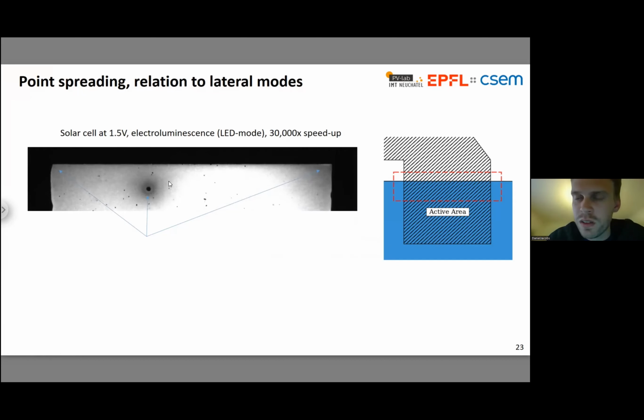So this was a solar cell device in which I stressed it at forward bias. It's an LED type test where I was applying forward voltage and just looking at the electroluminescence. The schematic on the right shows the region that I'm focusing on here. And the surprising observation was, I was expecting in this test to perhaps see something happening around the boundaries, the one-dimensional electrode edges of the device. Instead, I saw this degradation happening at the corners. You can see that the two corners that I've pointed out with the arrows here are the source of a propagating front of degradation, as well as this little spot, probably a contaminant particle or something that got into my cell, and which is already there in the T equals 0 photoluminescence image.